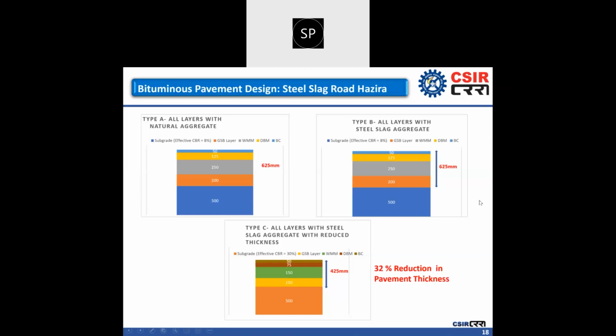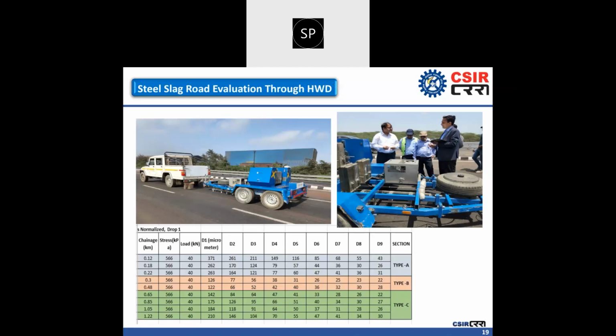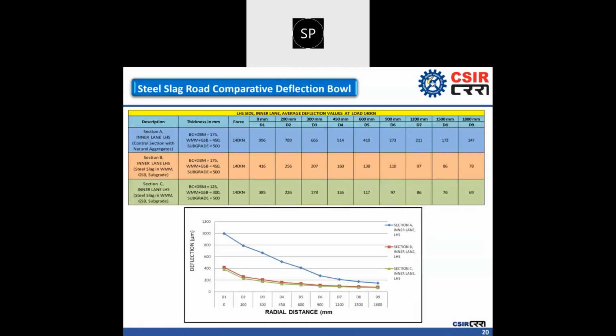processed steel slag aggregate. Now here you can see the structural evaluation which has been carried out through the heavyweight deflectometer on the steel slag road section. One of the important findings of this study is that in the case of the conventional road, at 40 kN impulse load, the deflection is around 260 to 371 micron, and this deflection is reduced by 50 to 60% when we tested it on the steel slag road section. Type B is with the conventional thickness and type C is with the reduced thickness. Despite having 32% reduced thickness in the pavement, the steel slag road is showing significantly lower deflection under the impulse loading. By virtue of that, we achieved the highest structural stiffness inside the road.